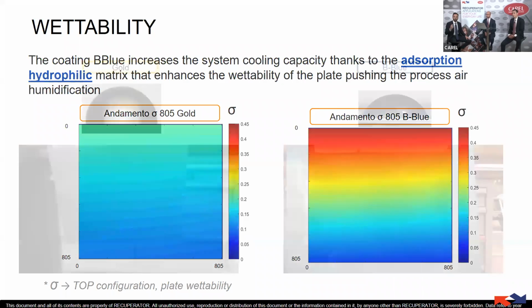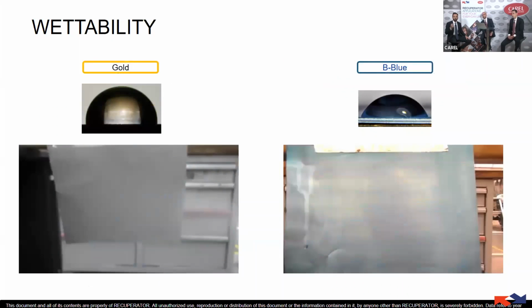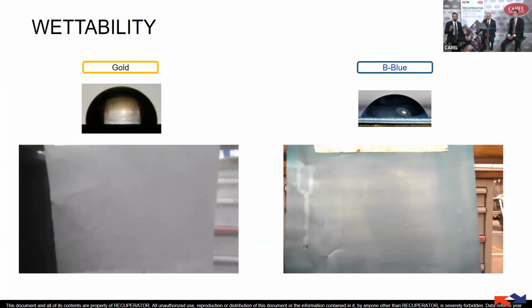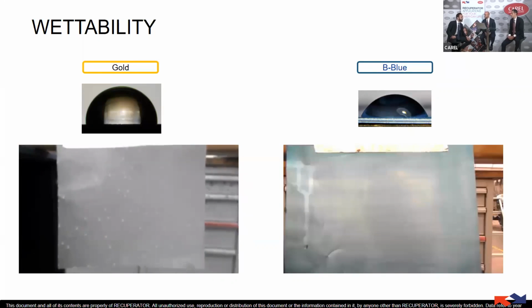But let's see something practical. We have two videos that can for sure explain better than me what hydrophilic absorption means. The first video is with the epoxy protection. As you can see, we spray water on the epoxy protection, we have droplets, we still have droplets, we don't have an even film of water on the surface. And so we have the drops on the surface. Exactly, yes. It's not absorbing, it's just keeping, we have small droplets around the surface.